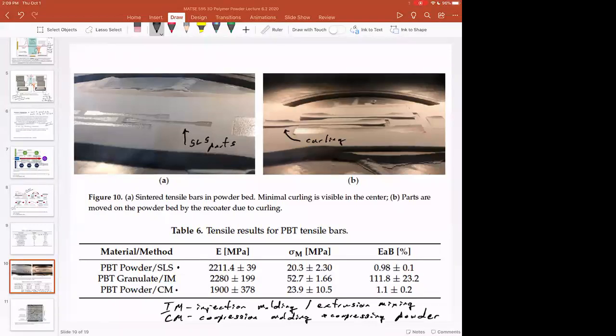And so if we look at the mechanical properties, the Young's modulus is pretty good, right, for all of these. Compression molding's a little bit lower, but let's say on the order of 1900 to 2200 megapascal. That's not too bad. However, the elongation to break is a real issue, including the maximum strain, the maximum stress at failure. When you process from powder, you're not able to elongate the sample as well. It's a little bit porous.